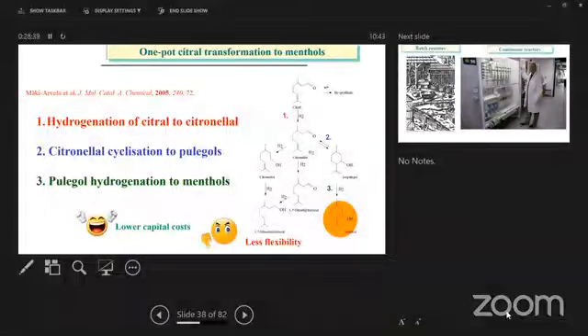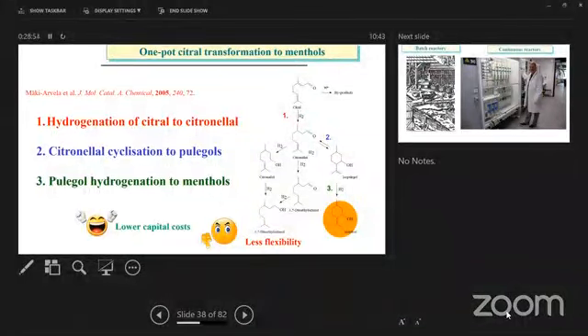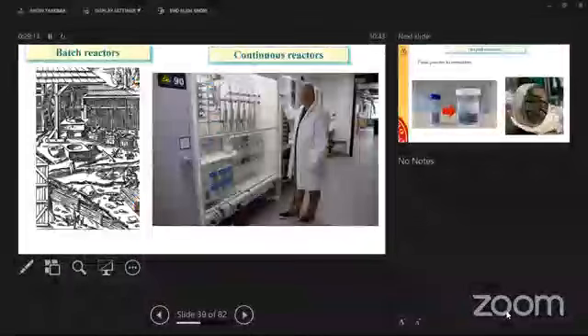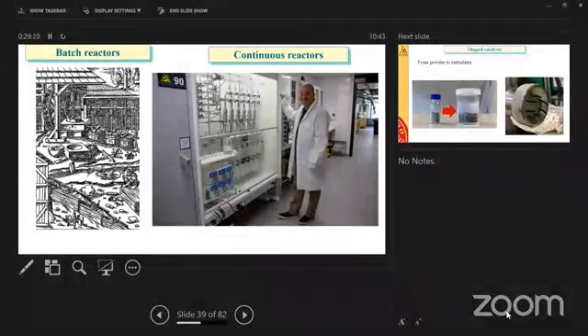Low capital costs. But then the downside is lower flexibility, which means that all three steps, they should be conducted at the same conditions. When somebody is telling you that one pot is very good, now, sometimes yes, sometimes no, because then we have to find a compromise, because the optimal conditions for each and every step might not necessarily be the same. So you might have changes in the pressure or whatever it would be, atmosphere or temperature. But in this particular case, for one pot citral transformation, it's possible to find reasonable conditions. And we started with this one pot synthesis many years ago.